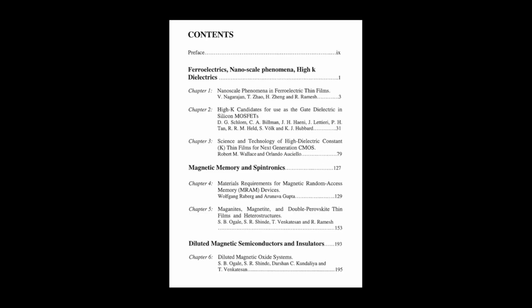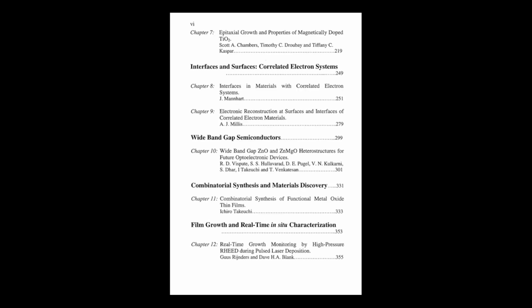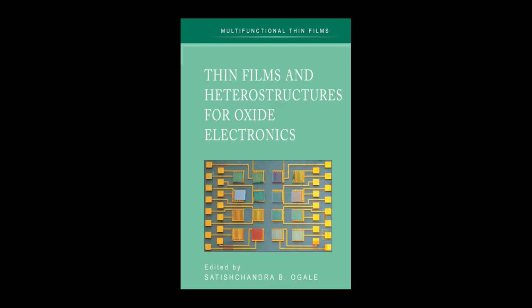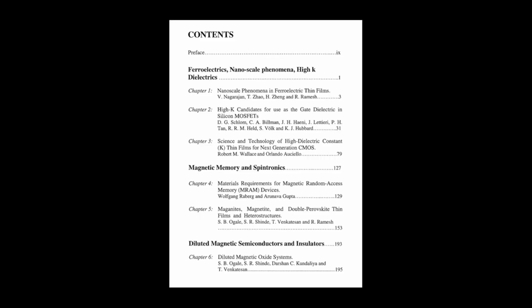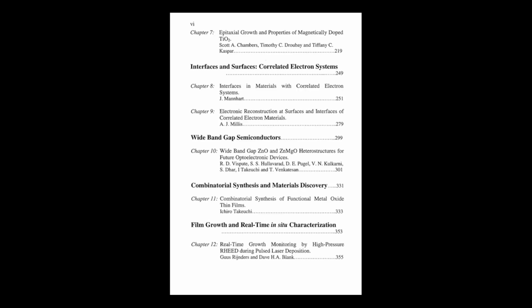Chapter 13 also touches on a few other advanced pulse deposition techniques. One is ion beam-assisted deposition, or IBAD. That sounds different. It's not just about depositing material. No, IBAD is about actively controlling the crystalline orientation of the growing film, even if the substrate itself is poorly ordered or randomly oriented. How does that work? You're hitting the film with ions while it grows. Yes, you have your deposition source, could be PLD, could be sputtering, but simultaneously you direct a low-energy ion beam at the growing film, hitting it at a very specific angle.